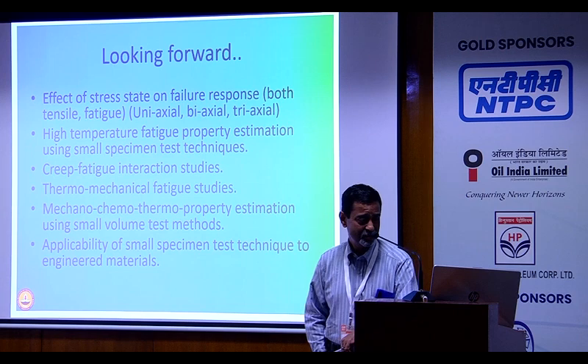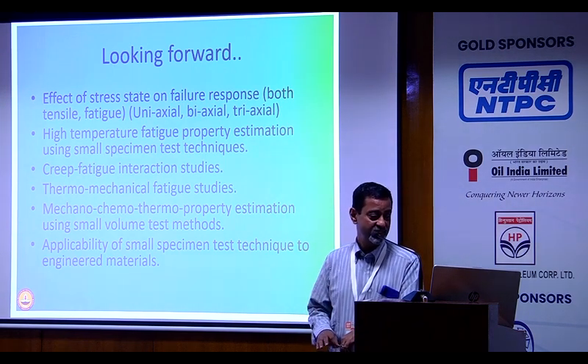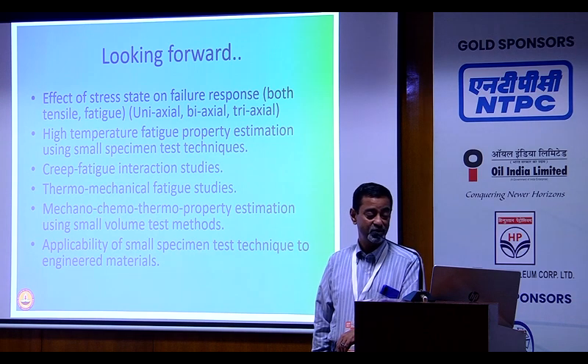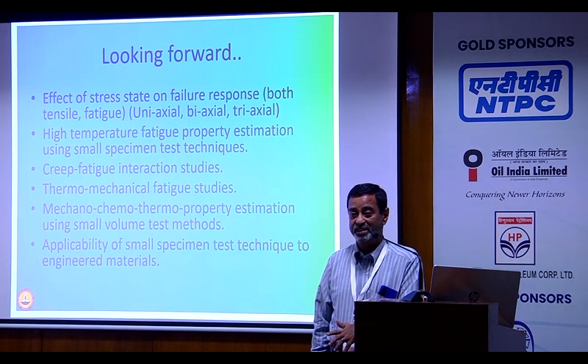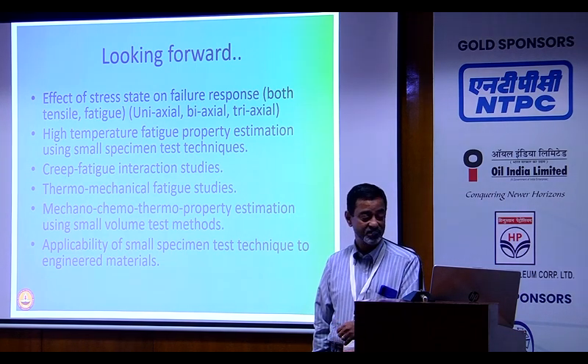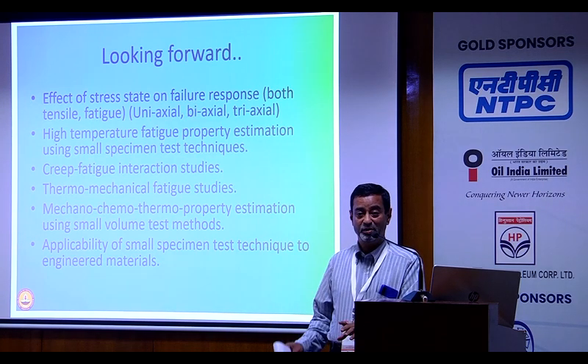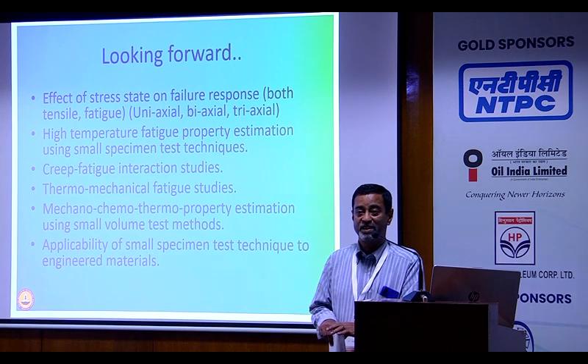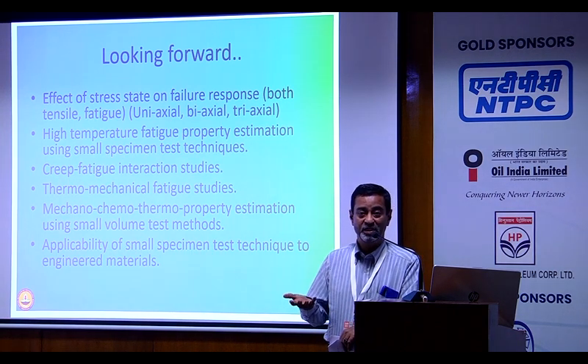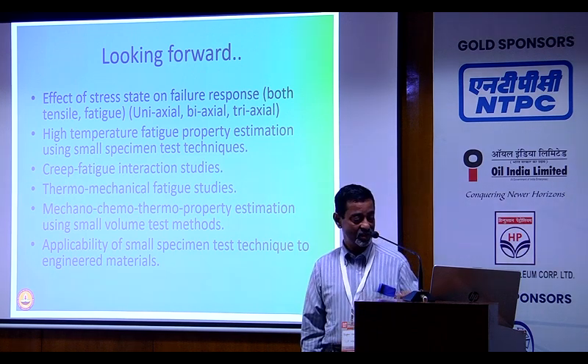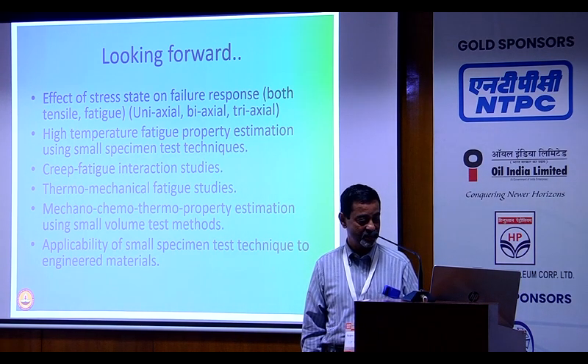So from an academic perspective, what we are looking forward to is the effect of stress state on the failure response, whether it's tensile or fatigue, or whether you are looking at uniaxial, biaxial or triaxial. And we also want to look at high temperature fatigue property estimation using small specimen test techniques. From the gathering over here, I see you are more worried about operating conditions of maybe less than 500 degrees centigrade, but there are some power plants where they are now looking at going to even higher temperatures.